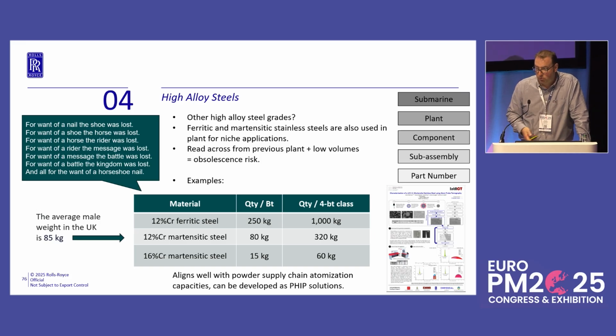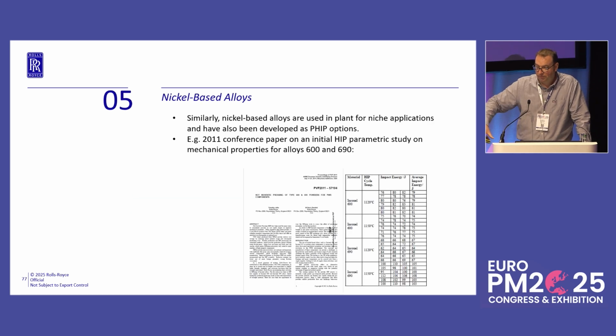You can see that top one's a 12 chrome ferritic steel, so it's just bordering on being stainless, whereas nitrogen is actually known to improve the pitting resistance. So yes, it might give a problem with the phase transformations, but it might also give us an advantage in the corrosion behaviour. The nickels, I won't touch too much on, but effectively, yeah, we've done them.